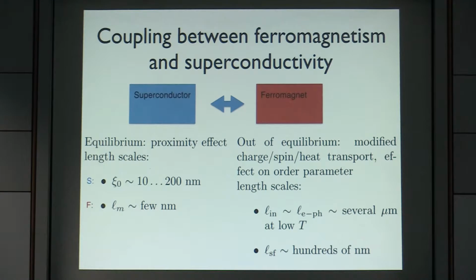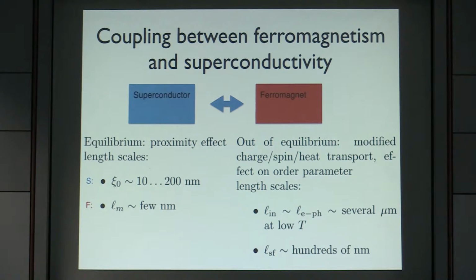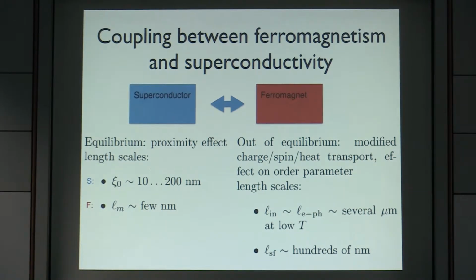Now, my title contained the words out of equilibrium. I would guess that the majority of the work on superconductor ferromagnet systems has been done on equilibrium properties, looking at the proximity effect from superconductors to ferromagnets, sometimes vice versa. These equilibrium effects usually show up at length scales related with coherence lengths. In the superconducting cases, coherence lengths are typically between 10 to 200 nanometers or so. Let's say aluminum is the 200 nanometers, then for higher TC you get smaller coherence lengths. In the magnetic case, if you look at just the penetration of the singlet correlations, you have the magnetic coherence length, which is a few nanometers at max, depending on the magnet.